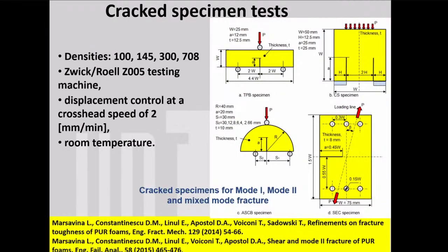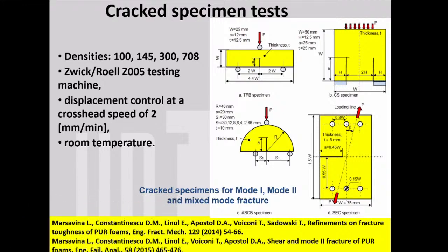The cracked specimens that we investigated were the single edge notch bend specimen loaded in 3-point bending, the compact shear specimen for mode 2 loading, the asymmetric semicircular bend specimen for mixed mode loading from pure mode 1 to pure mode 2, and also the single edge crack specimen loaded in Arcan grips for determining mixed mode loading. We used the same testing equipment, the same displacement control, and the tests were performed at room temperature.